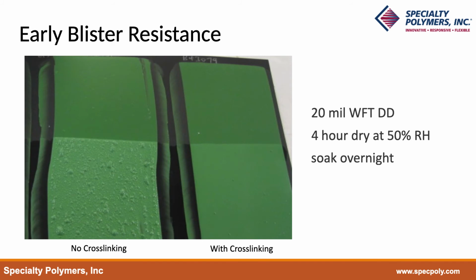We see a significant improvement in the early blister resistance. These two polymers were both all acrylic with a Tg of around 7 degrees C. They were the same except for the ambient temperature crosslinking in the paint on the right. We cast a 20 mil wet film, dried it for only 4 hours at room temperature and 50% relative humidity, then placed the panels in water and soaked them overnight. It's quite a severe test.